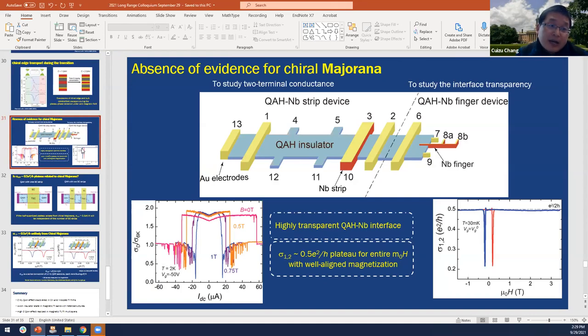And for the final part, about the quantum anomalous Hall and superconductor hybrid system: from our experiment, we didn't rule out the theoretical prediction, definitely. So we also didn't rule out this kind of configuration to detect the Majorana physics. I can only speak for the millimeter size. Millimeter size is very important in this kind of work. In a millimeter size quantum anomalous Hall and superconductor hybrid structure, we cannot use this configuration to detect the Majorana physics.